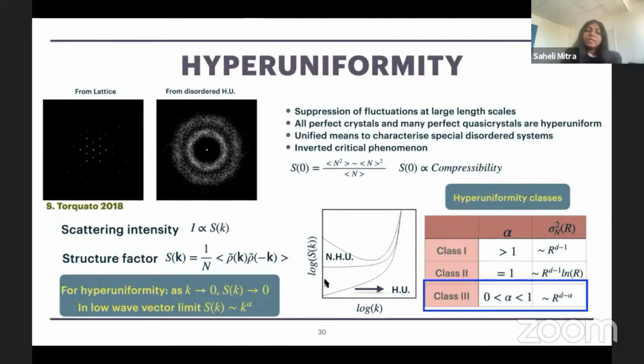So for a hyperuniform system, close to the origin, the structure factor will tend to vanish. In fact, in the low wave vector regime, we can fit a power law to the structure factor, and we can extract the exponent of the power law, alpha, which is called the hyperuniformity exponent. Depending on the hyperuniformity exponent, we can classify hyperuniform systems in different classes. This exponent is related to the number variance that we just saw in the last slide. For example, if the exponent is between 0 and 1, then the number variance will scale as r to the power d minus alpha in a d-dimensional system.